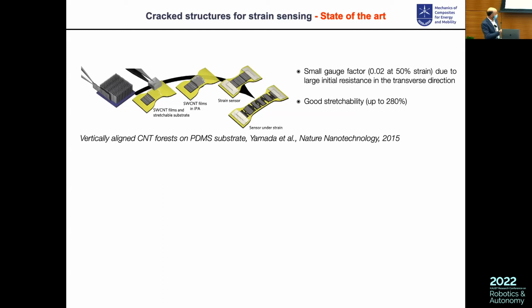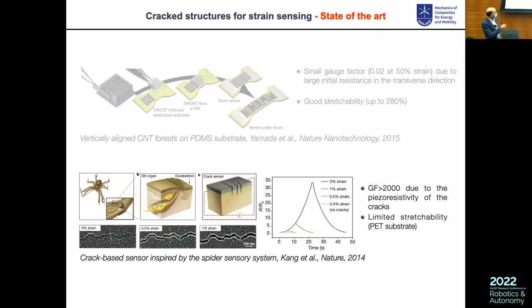And then another very well-known paper is this one. It's a metallic coating on a PET substrate. But same thing here, you introduce cracks in the metallic coating. Here you get a very high gauge factor, more than 2000, because you directly play with the opening of the crack. So if you have a crack that is touching, as soon as you separate it, you are losing the conductivity and your gauge factor is increasing, right? But of course, since you are using a metallic coating, as soon as you separate the crack, you are losing the conductivity on a PET substrate. So same thing, same dilemma. I mean, either you are very stretchable with low gauge factor, or high gauge factor but non-stretchable.